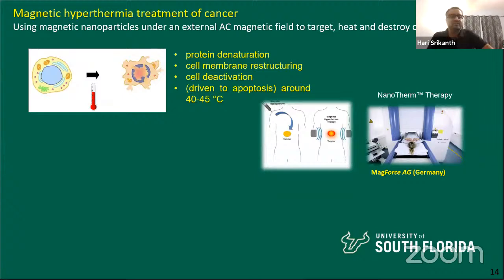The answer is simple. What we do is that we take magnetic nanoparticles and apply an oscillating magnetic field with large amplitude, okay? Because we need to completely go over the hysteresis loop again and again, okay? And at high frequency. And that causes heat, and that will destroy cancer cells. I'll explain to you the physics behind this.